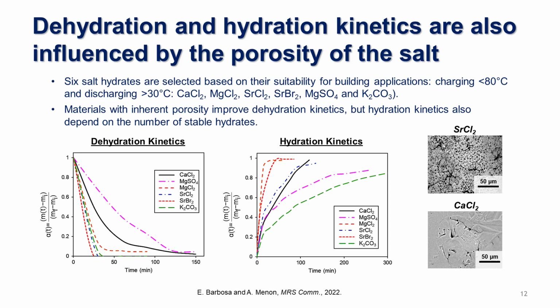So here's a list of the different salts that we work with. There's 6 different thermochemical salt hydrates. Again, some of these are very common materials like calcium chloride, magnesium chloride, and magnesium sulfate. And then there's the strontium salts, which tend to be much more stable, but also more expensive. And so we're trying to characterize those materials as well.